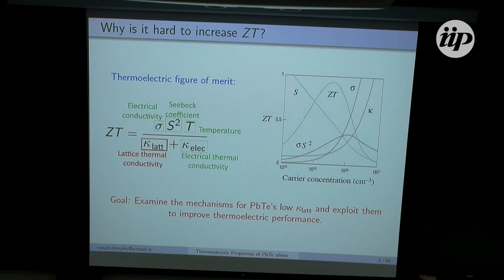So the effectiveness of a thermoelectric material is given by the figure of merit, ZT, which depends on the electrical conductivity, the square of the Seebeck coefficient, the temperature, and the lattice and electrical thermoconductivities, respectively. Now, increasing the figure of merit can be a little difficult. What ordinarily happens is that as you increase one, you end up decreasing another. So what we want to do is look for ways around this block. The lattice thermoconductivity is somewhat decoupled from other properties. How we're going to tackle this is we're going to take a look at lead telluride, which has a characteristically low lattice thermoconductivity. We're going to look for the reasons behind this to try to exploit them to reduce the thermoconductivity even further.